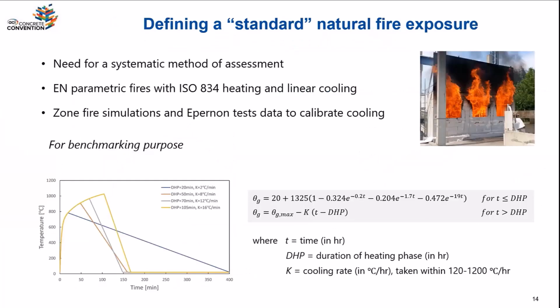So to do that systematically, we adopted what we call a standard natural fire exposure. So that's not the full performance-based design where each fire depends on each compartment, taking into account the fuel, etc. Here we want something systematic, so we heat always with the same time temperature curve, and then we have a linear cooling phase. And so by subjecting different members always to this type of standard time temperature curve, but with a cooling phase, we can benchmark and compare the vulnerability to the cooling phase.